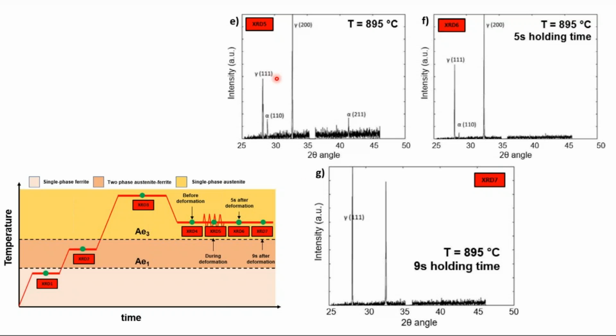What is interesting here is that when you conduct the deformation in that austenite field, you are going to see some ferrite appearing. So what is the conclusion of that? That while you apply deformation in that field, you are going to create ferrite. After 5 seconds, you can see barely a small peak of ferrite. And after 9 seconds, all the evidence of an existing ferrite has disappeared. So that's the main point of this. You can then produce a material with some ferrite within your material. I don't know why, or if it is useful or not. Or you can also avoid the formation of ferrite if it is deleterious for your material. Anyway, as shown here, you can use this type of facilities to better develop your processes in the industry.